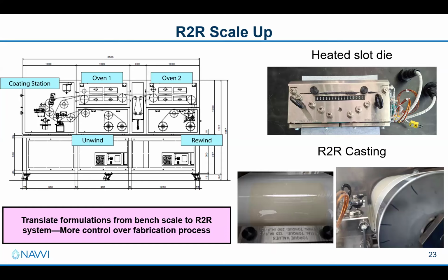And just as some examples, we've got a heated slot die, where we can use both temperature and the inlet flow rate alongside the internal configuration of the slot die to make membranes of predefined width and predefined thickness for a wide variety of different materials of very different rheologies. We can go down to very, very inviscid, very low viscosity electrodes. So these could be catalyst layers in different devices that people might use in water purification applications. And these could also be fairly thick membranes, as we'll show in a few slides.